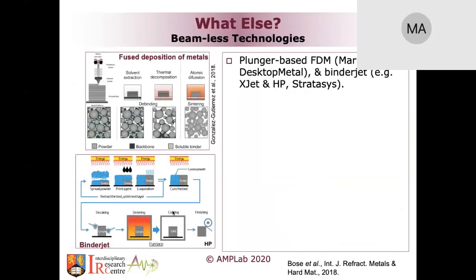Again, what else can be done? There are, as you know, beamless technologies that have been coming out in previous years. Techniques like the FDM type techniques such as Markforged and Desktop Metal, or the binder jetting type techniques by XJet, HP, and Stratasys. Those are in a sense powder metallurgy techniques. In the Desktop Metal type technique, you extrude the powder surrounded by resin, debind, and then sinter. The same is the case with binder jetting. You basically spray the binder and then debind and sinter, and then potentially even HIP.